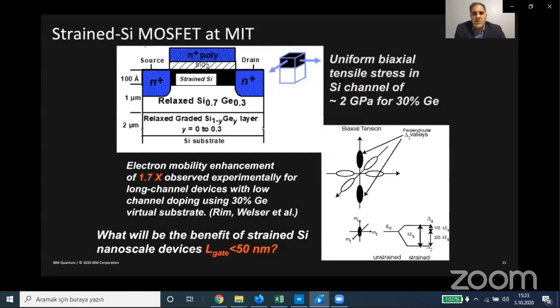And let me just describe strain engineering. This is from our group at MIT from the early 2000s. We worked on a substrate strain method where we grow, using UHVCVD, a thin layer of silicon on silicon germanium, and due to the lattice mismatch between the two layers, the silicon on top here is under tensile stress. Actually, the amount of stress is quite high. It's around 2 gigapascals for 30% germanium. Because the lattice constant for silicon germanium is higher, the silicon on top is under tensile strain, biaxial tensile strain.